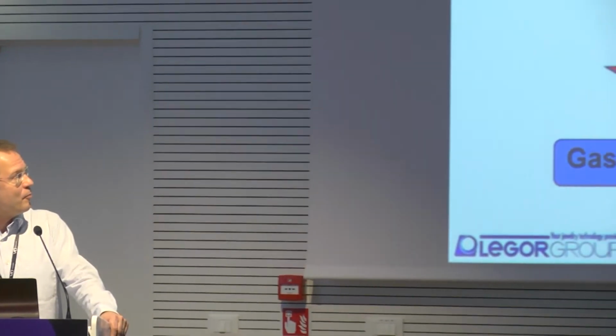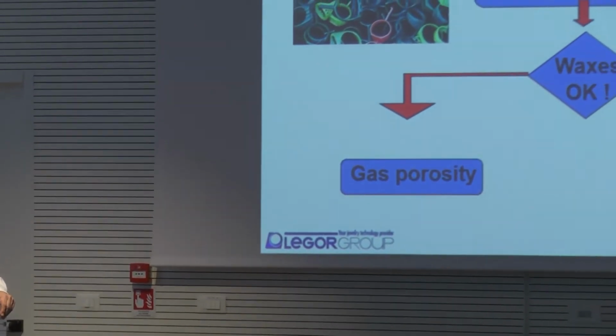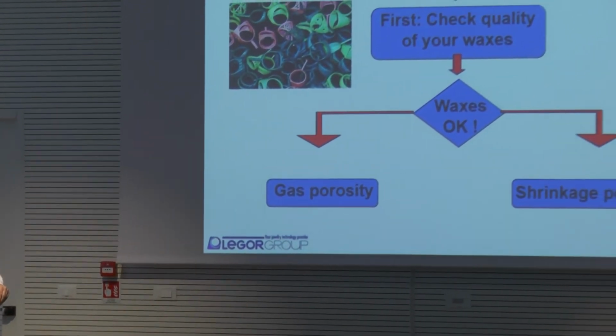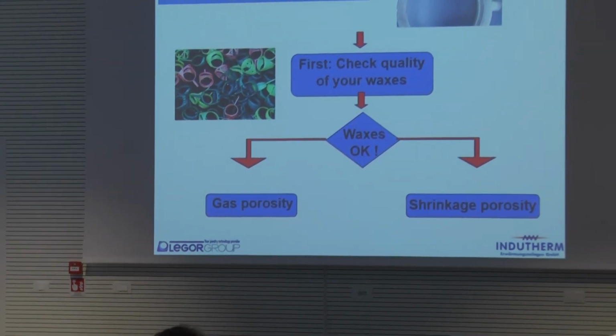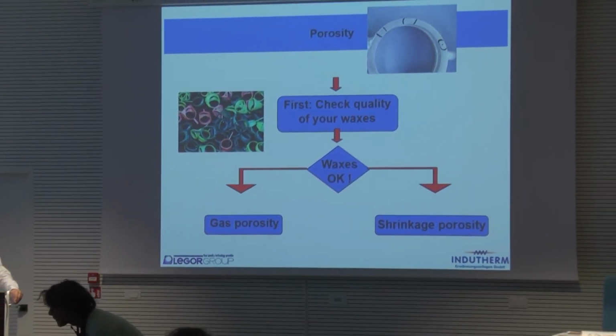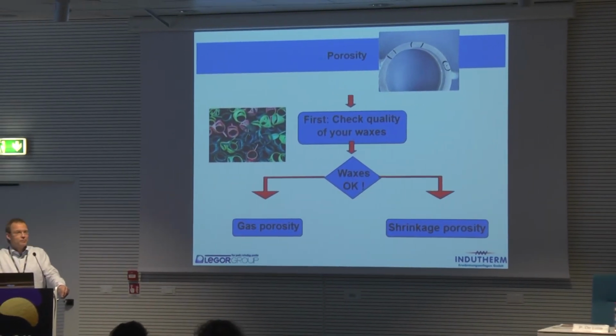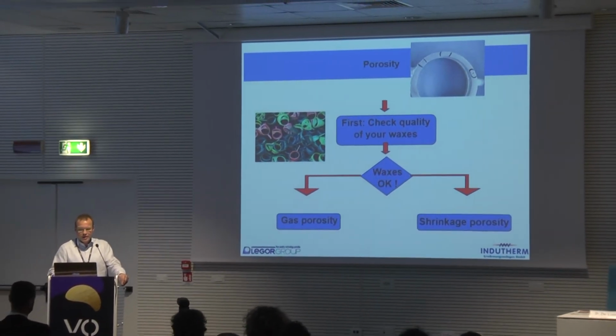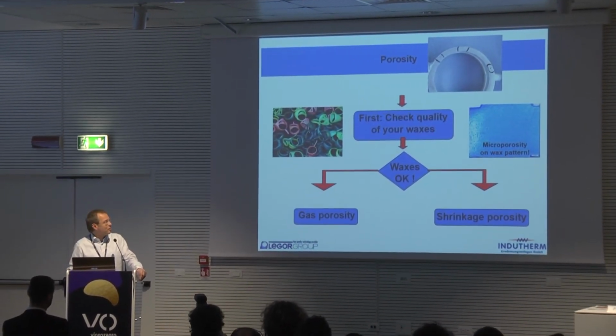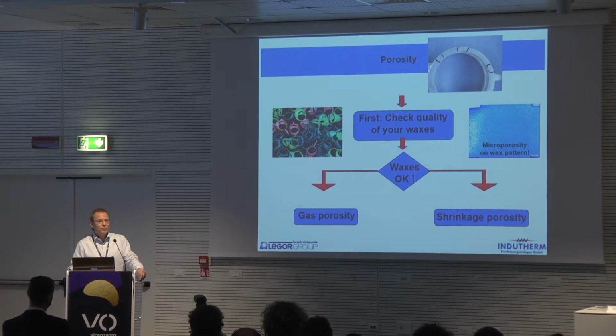First of all, a general comment: if we talk about porosity and pinholes on an as-cast surface, in many cases, we can trace them actually back to wax defects. So the first recommendation will always be, if you have issues with porosity or pinholes on your surface, check the quality of the wax. Many cases, we can find porosity already on the waxes.